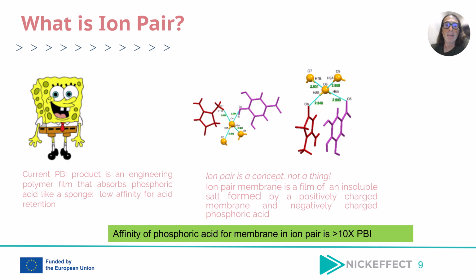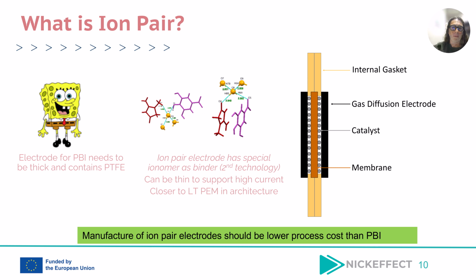It's not a thing. It's a membrane that forms a film, and you actually make an insoluble salt between positively charged membrane and phosphoric acid, and the salt binds tightly. In fact, it actually binds 10 times stronger than the PBI does. This is what allows us to work at higher temperatures, higher powers, and be more stable. But there is a second part to the story of ion pair. Not only is it a film, but it's an electrode technology. So there are two technologies wrapped into one.